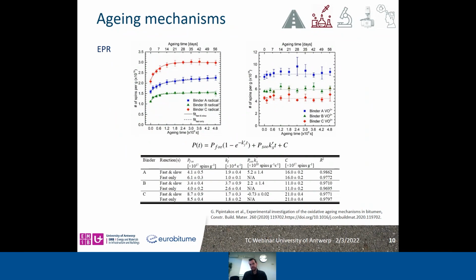On the other hand, metal species like vanadium ions were almost unaffected by aging, considering the standard deviation of the replicates that were performed. And this, based on different reports and publications for crude oils, not for bitumen, can be an indication of the vanadium content of bitumen in this case, and further research as well will investigate if we can trace back from this the source of bitumen.